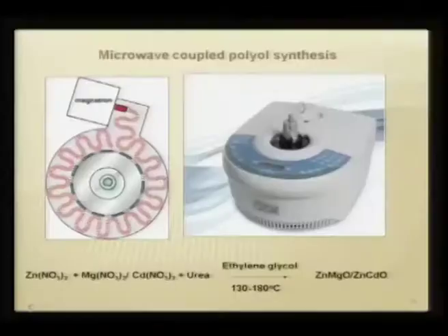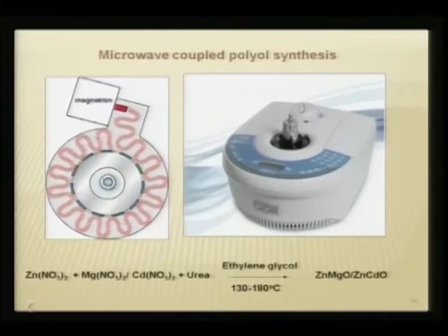We also saw how zinc sulphide can be tuned by substituting different transition metal ions to get the desired color purity, and we looked at doping zinc, cadmium and manganese together to get a full width at half maximum beyond 150 nanometers, thereby trying to harvest white light.